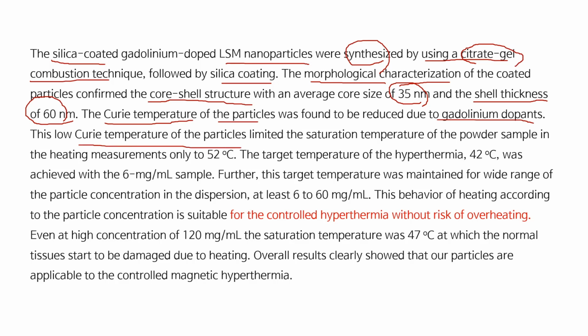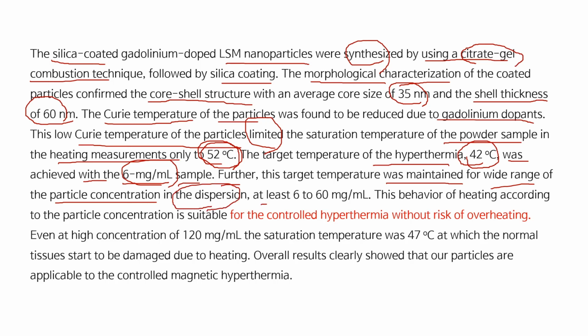This low Curie temperature of particles limited the saturation temperature of the powder sample in the heating measurements to only 52 degrees centigrade. The target temperature of hyperthermia, which is 42 degrees centigrade, was achieved with a 6 milligram per milliliter sample. Further, this target temperature was maintained for a wide range of particle concentration in the dispersion, at least 6 to 60 milligram per milliliter. This behavior of heating according to the particle concentration is suitable for controlled hyperthermia without risk of overheating.